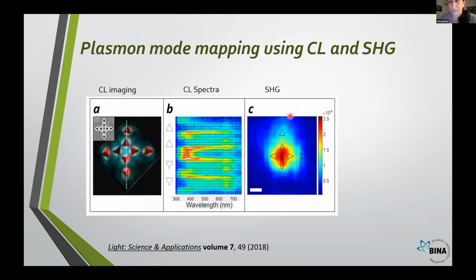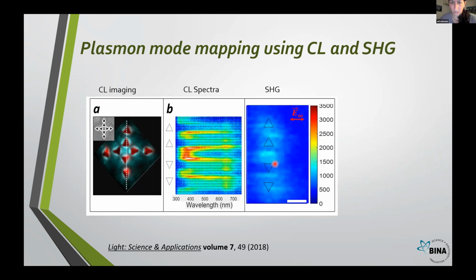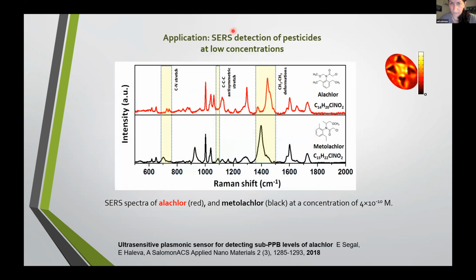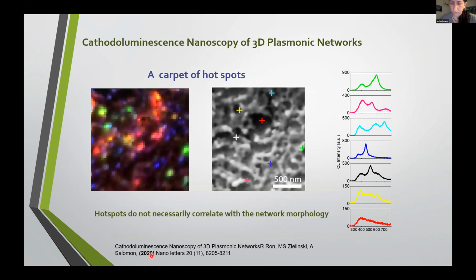correlated with second harmonic generation mapping, because indeed we have the hotspot in between the cavities, and we can use it, of course, for applications like surface enhanced Raman spectroscopy to detect pesticides at concentrations as low as 4 times 10 to the minus 10 molar, due to these hotspots.